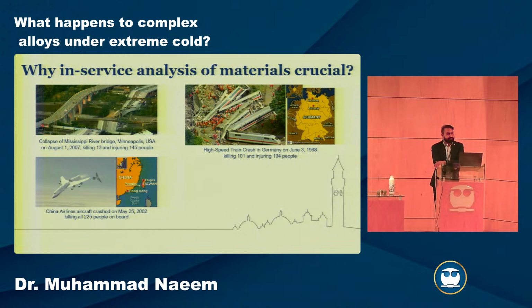And then this was a high-speed train accident which happened in Germany in '98, and that was also caused by a wheel of the train, where there was a single fatigue crack, and that ultimately led the train to divert from one rail to another and derail. I mean, it just moved out of the track, and it resulted in more than 100 people being dead and almost 200 being injured. So these are really sobering examples. Of course, these are extremes, but people got killed.